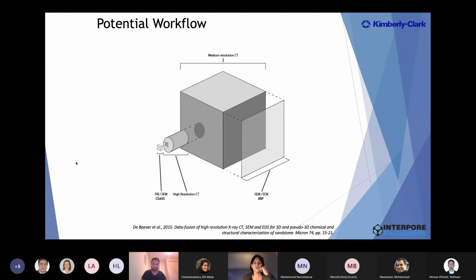So a potential workflow could be: you first take a bigger sample, scan it at medium resolution. Maybe you've also polished the sides, so you can combine this with scanning electron microscopy combined with EDS in order to get chemical information, and you can then do mapping or registration of what you see with SEM-EDS combined with CT to get an estimate of the composition. You can also combine this with X-ray fluorescence.